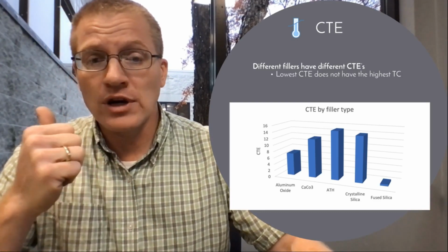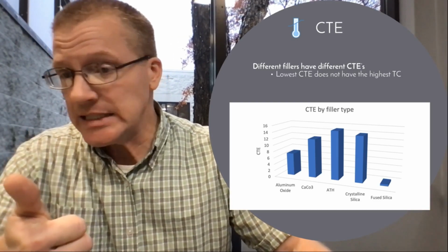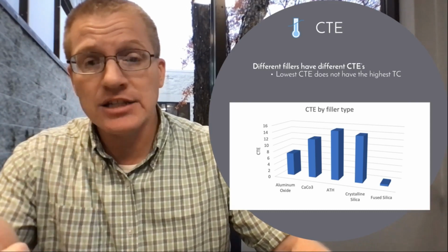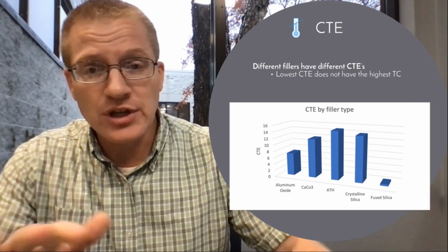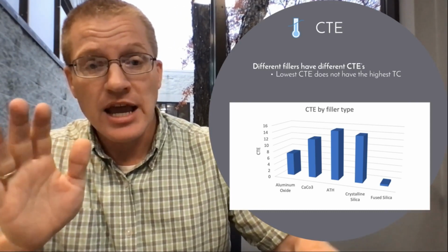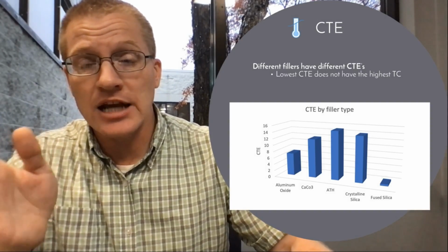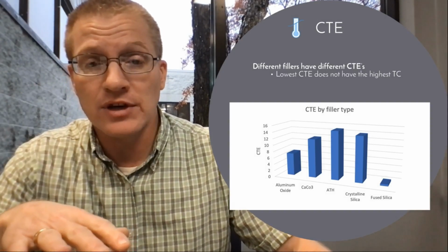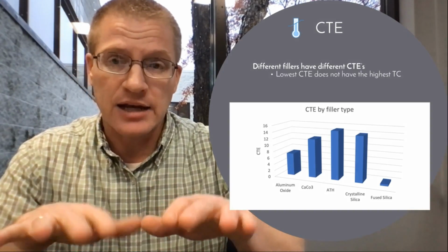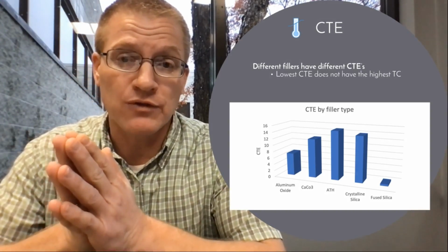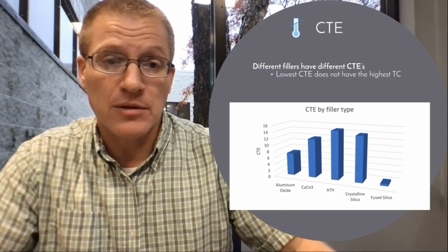So if you're looking for a combination of the lowest CTE you can get and the highest thermal conductivity, you're not always going to get the combination of those two things, because as we saw earlier, fused silica actually has a lower thermal conductivity. So there's a little bit of a balancing act that you need to look at when you're looking for certain properties in your particular polymer.